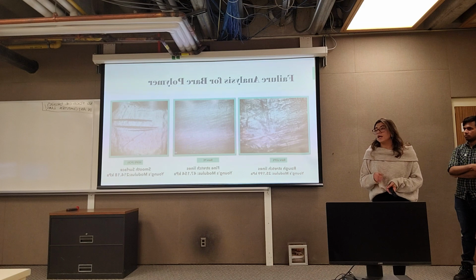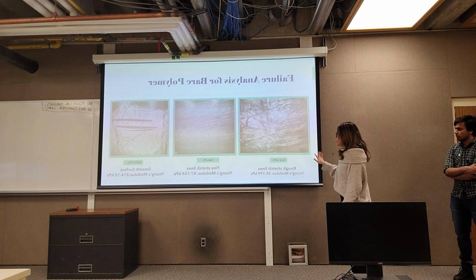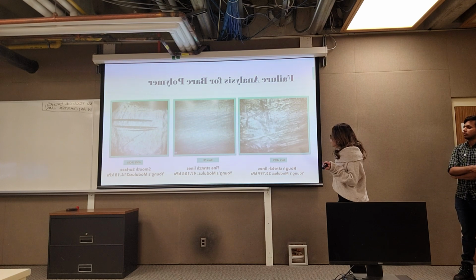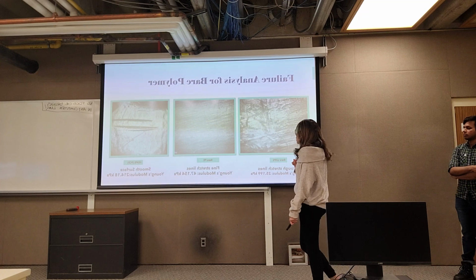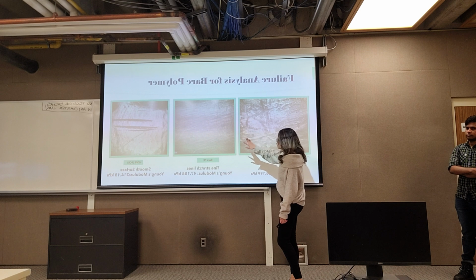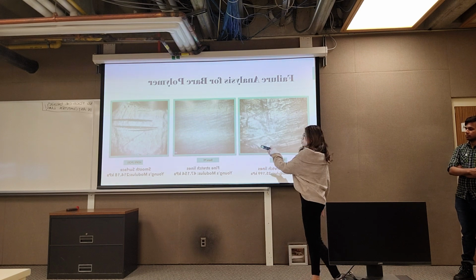This was in line with our values of tensile testing, because ductility is inversely related with the Young modulus. So the PE and the LDPE got the lowest values of Young modulus. As well, we saw that the surface of the bare PE has fine stretch lines, the bare LDPE rough stretch lines, and the HDPE, instead of having a stretching, we observe a relatively small surface.